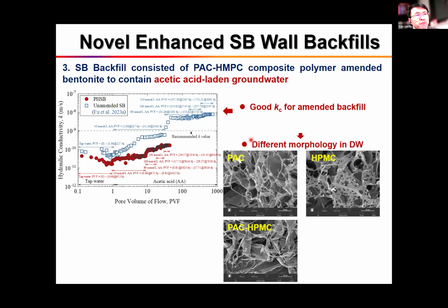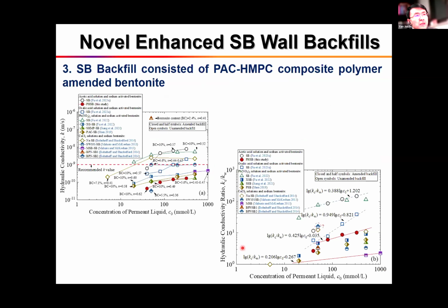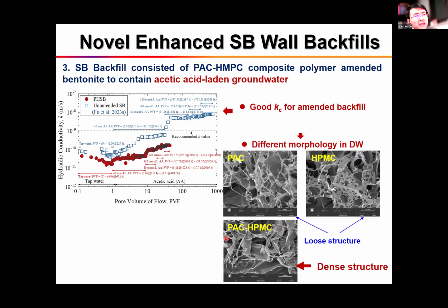Interestingly, we also find a different morphology in distilled water for single polymer and composite polymer. For single polymer, PAC alone or HPMC alone, we find the polymers form a relatively loose structure. However, for the composite polymer, they form a dense structure. I mean, the dense structure of the composite polymer hydrogel. So that will be the reason why the composite